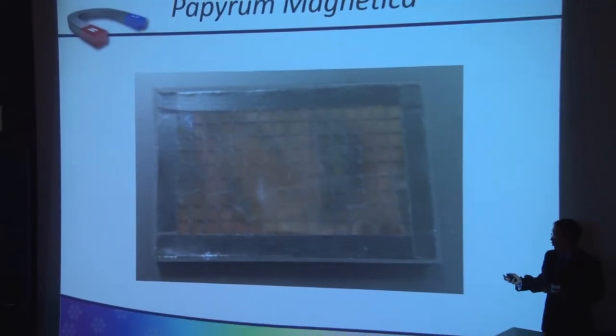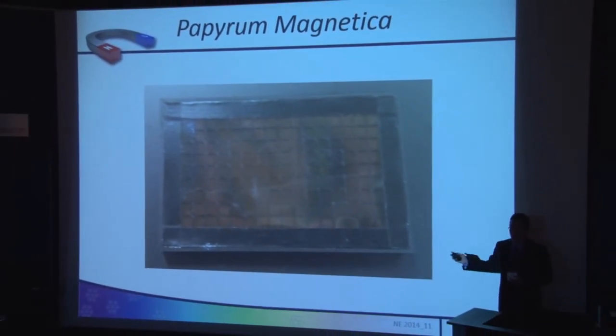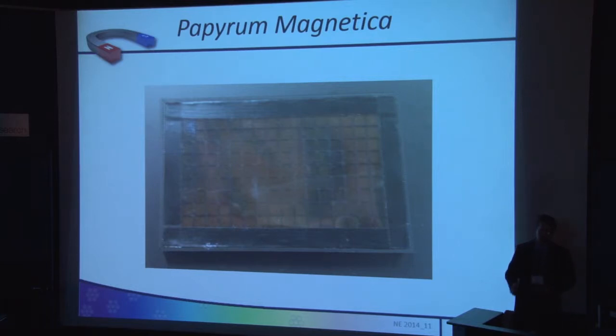But mainly from this, we were able to demonstrate a proof of concept. However, it was not very accurate in being able to draw stuff, mainly because we needed a large magnetic strength in order to magnetize the hysteresis layer underneath this prototype.